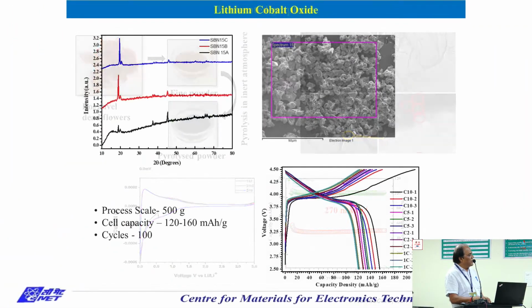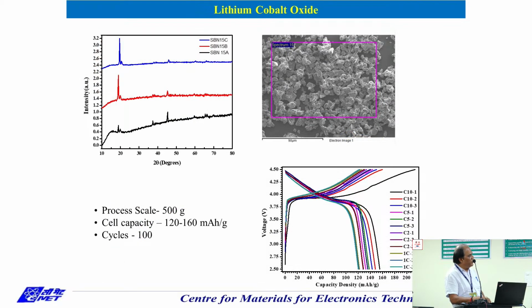Then lithium cobalt oxide is one of the new compounds we have developed for this, and we found that again it has a very stable capacity of 160 milliampere hour per gram. It is a good capacity.